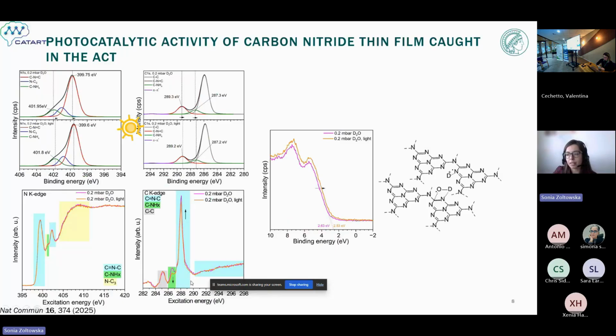And also, if we compare the valence band XPS spectra, we can see slight shifts towards lower binding energies, because at that moment the surface has slightly lower oxidation potential. We interpret those spectroscopic reflections as a rather stable structure, which supports the proton-coupled electron transfer mechanism of hydrogen formation from water. And this is indeed photocatalysis caught in the act.